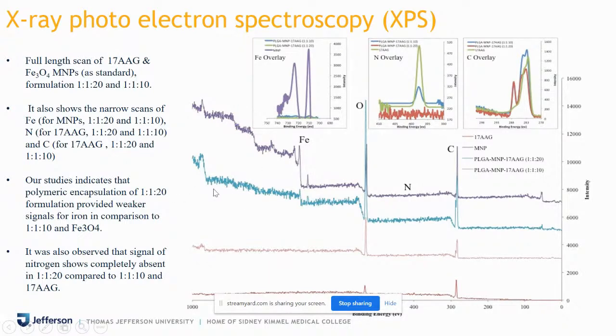Just to see that we can get Fe signals, these are standard. Then you have a blue color line which is a PLGA MNP 17 AG 1:1:20. So I told you that I made two polymeric ratios to see the impact of polymer on drug encapsulation and the release kinetics. So the blue color is about 1:1:20: 1 part of drug, 1 part of Fe3O4, and 20 parts of polymer. Similarly, 1 part of drug, 1 part of Fe3O4, and 10 parts of polymer. So these two formulations were studied using XPS.